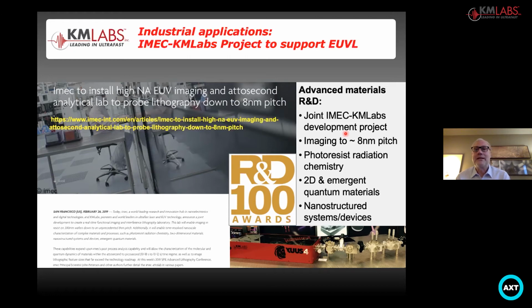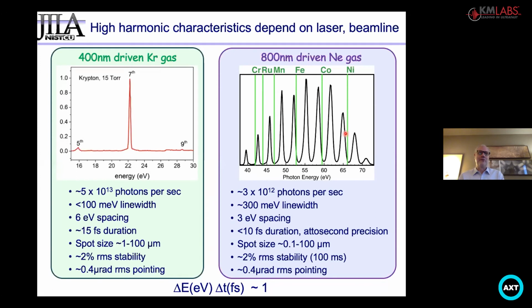The source is a combination of the femtosecond laser system, and you want a high power because the conversion efficiency for high harmonics varies between 10⁻⁴ and 10⁻⁸. So you want to start with a whole lot of photons. You get a lot of photons out, plenty to do these experiments, but you do want an advanced femtosecond laser. And then there's the frequency conversion step and the beamline, which is what we've commercialized in the Zeus 4, which is shown in a picture down in the corner there.